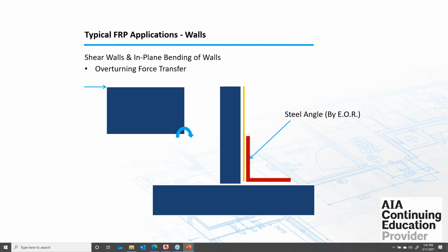If you have any overturning going on, if you need force transfer into the slabs to help tie everything together, you can do that with a steel angle bonded to the FRP, and then you would anchor that angle down into the concrete. This would be a great example of what I was talking about earlier regarding the conductivity of the carbon and having to pay attention to that. In this case, we would want to either put a piece of fiberglass in between the carbon and the steel angle, or just make sure that we put in a lot of extra epoxy to make sure that there's no contact between that carbon and that steel, so we don't get a corrosion cell starting and then corroding the steel plate that you're relying on. So good example of that.